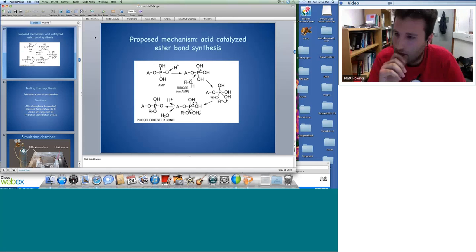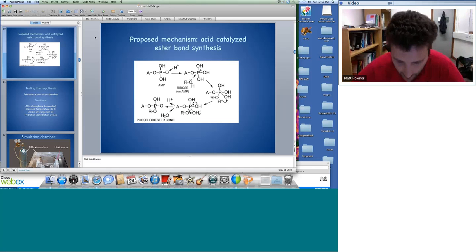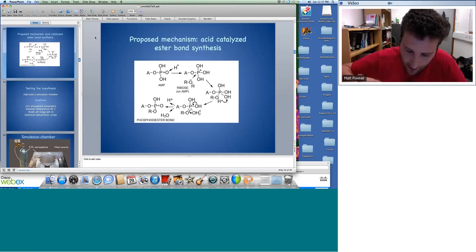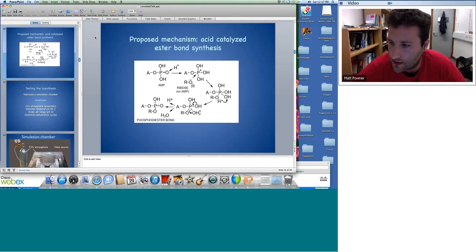I like that. And we've done quite a lot of transphosphorylations in the presence of ammonia. We used it in our 2009 paper to make mononucleotides. If you do these in relatively long glass vials, you can see the ammonia deposit, and you can redissolve the ammonia and see that it's ammonia on the sides of the vial. So I'm very confident ammonia is lost from these reactions.